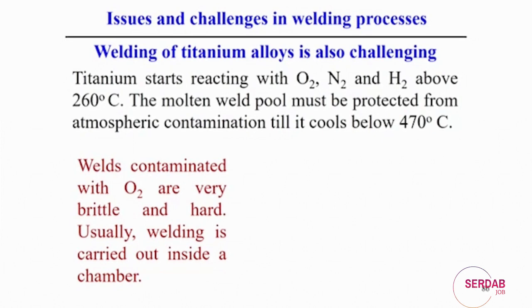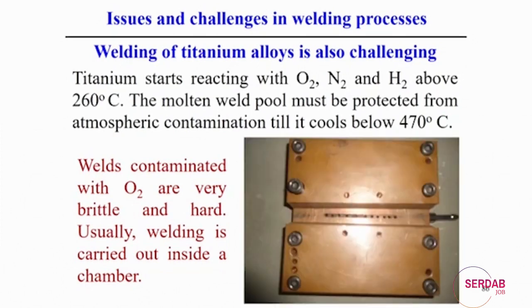So, to avoid the atmospheric contamination, in most cases we do the welding of titanium alloy inside a chamber, or some modification can be done when you try to weld titanium alloy, so that this oxidation problem can at least be reduced. One methodology for welding titanium alloy is to change the fixture used for welding, for example two sheet plates. Here we can use a copper plate, and we can use purging with extra shielding gas.